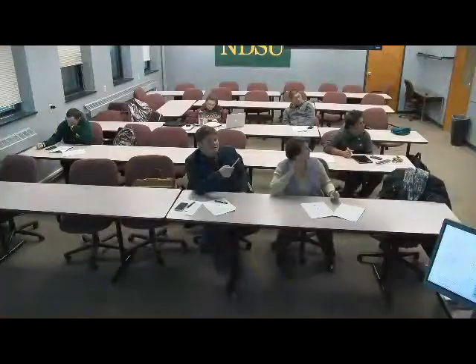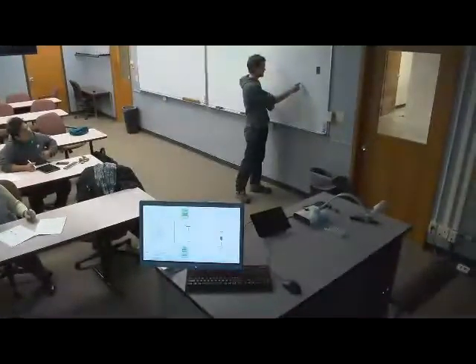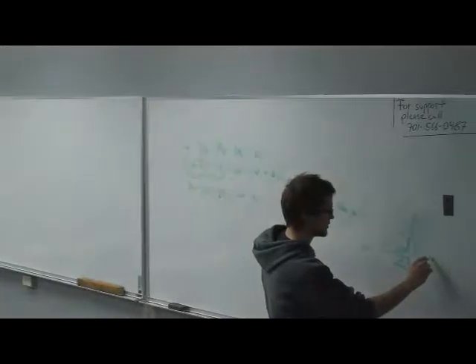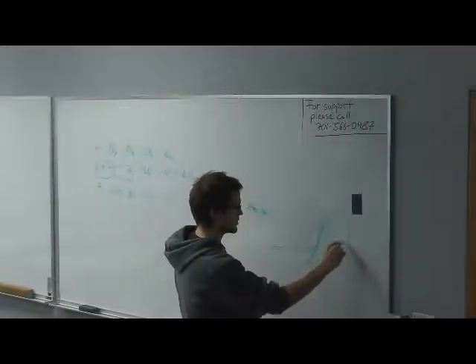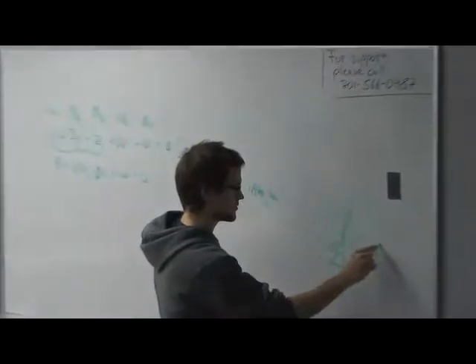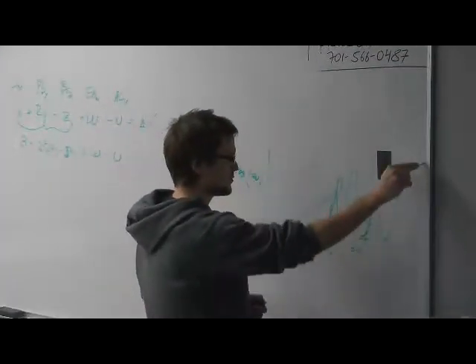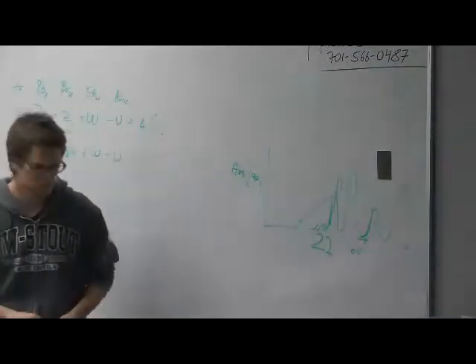How do I get back to this slide? And just very quickly, when you do your calculations, are you including spin-orbit or not in this case? That one. Or you can do both. You can do both. That one's spin restricted. Is there another color? If you do spin-orbit, this one actually increases a little bit, and then it follows. Your first peak increases in intensity, yeah, by about four times. Then it follows the same trend after that.